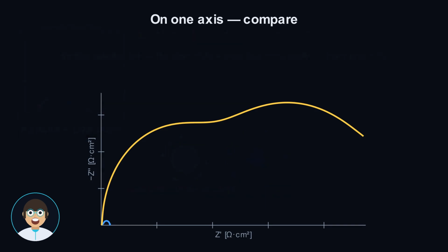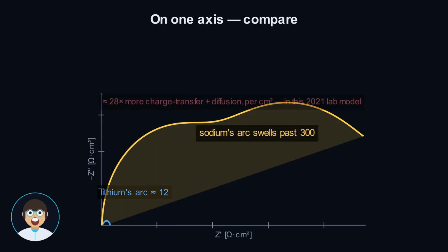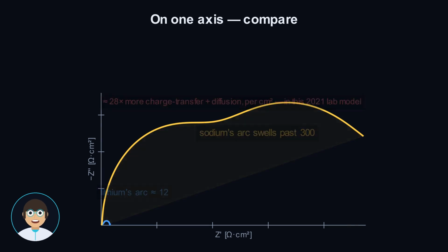But now follow the arcs. Lithium's charge transfer loop is small, around 12. Sodium swells past 300. In this pair of models, sodium's chemistry is far more sluggish at the surface and slower to diffuse within. So sodium wins on ohmic resistance and lithium wins on the reaction. No clean knockout, a split decision.